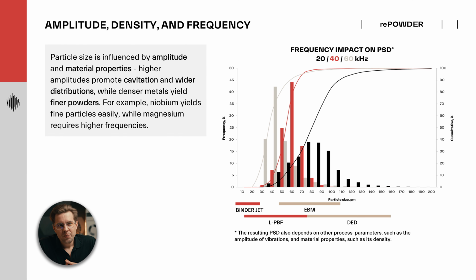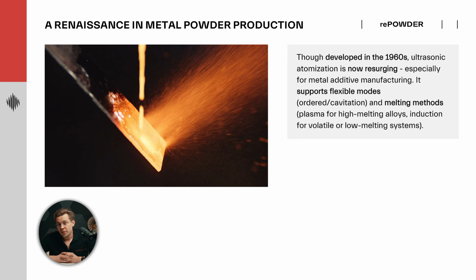Except for frequency, there are other factors that influence the effectiveness of ultrasonic atomization. One is amplitude. The higher the amplitude, the more we are in cavitational mode, and the broader the particle size distribution. The lower the amplitude, the more mono-sized particles we get. The others are material properties. The higher the density, the smaller the particles generated. The lower the density, the larger the particles generated. For example, getting fine particles with niobium is pretty easy, while getting fine particles with magnesium requires a higher frequency to achieve the same effect.